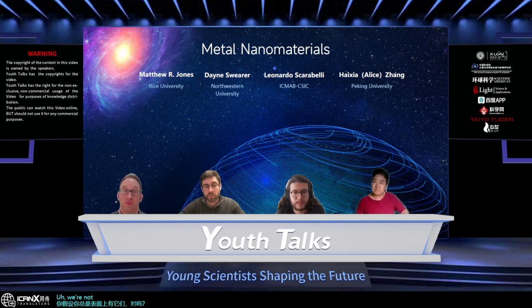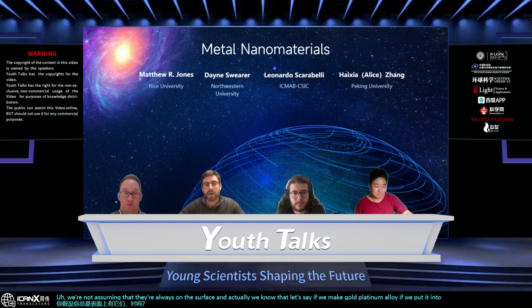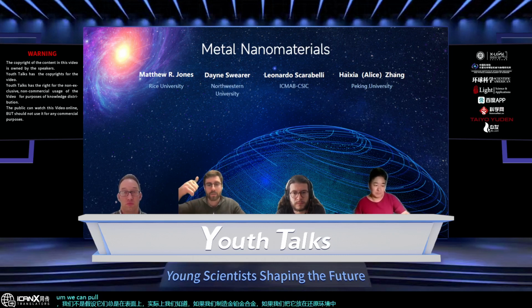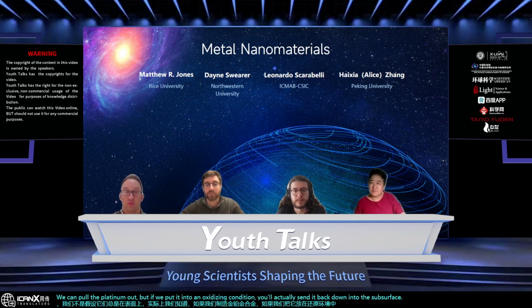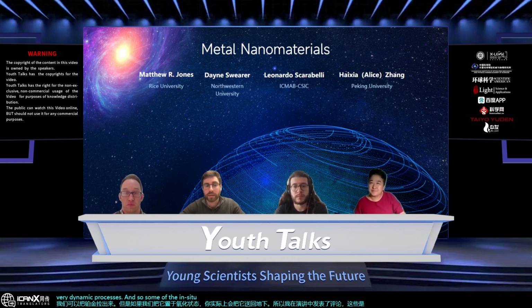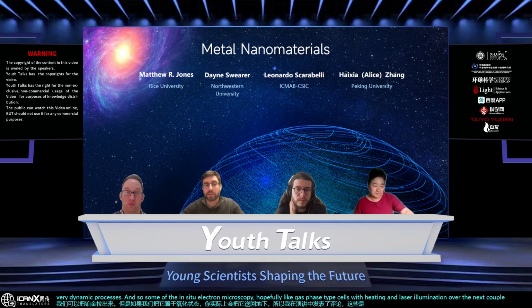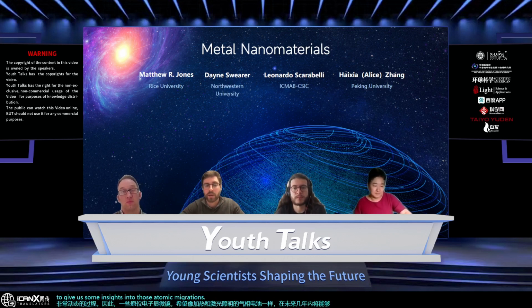We're not assuming that they're always on the surface. And actually, we know that if we make a gold platinum alloy and put it into a reducing environment like hydrogen, we can pull the platinum out, but if we put it into an oxidizing condition, you'll actually send it back down into the subsurface. And so I did make the comment during the talk, these are very, very dynamic processes. And so some of the in situ electron microscopy, hopefully like gas phase type cells with heating and laser illumination over the next couple of years, are going to be able to give us some insights into those atomic migration patterns and how that all plays a big part together.